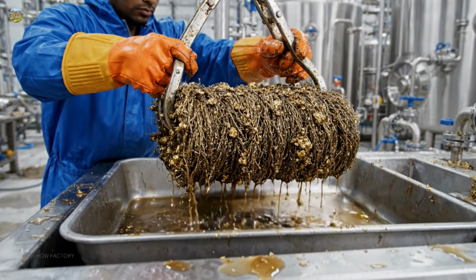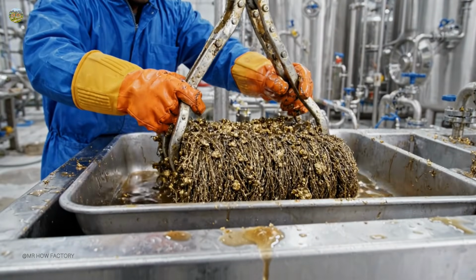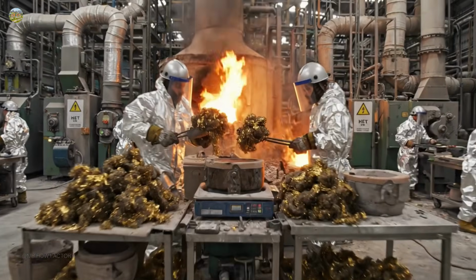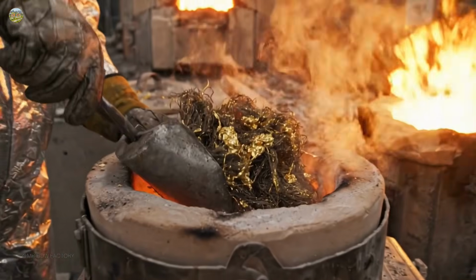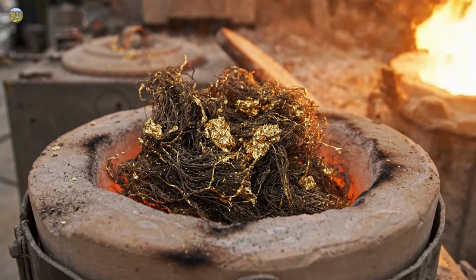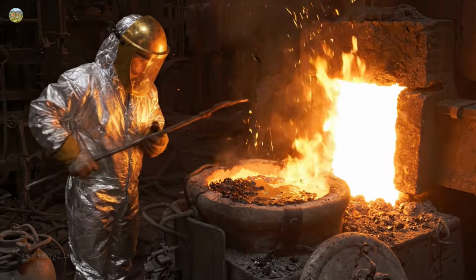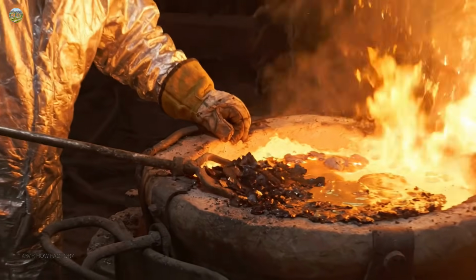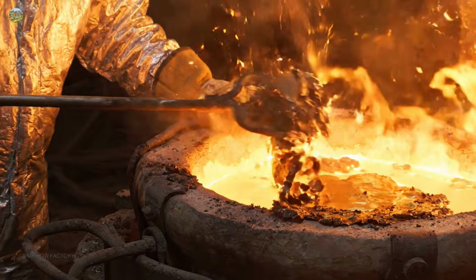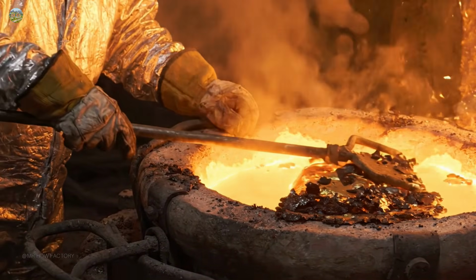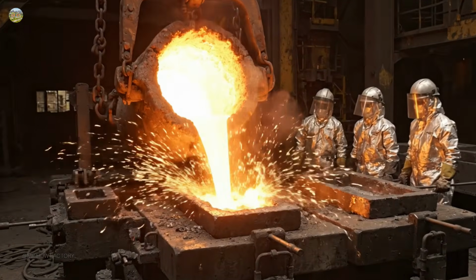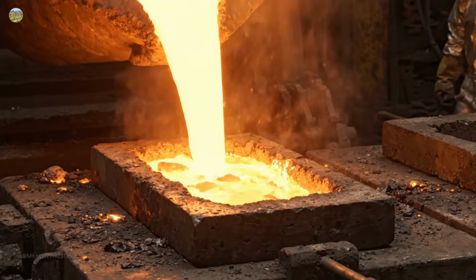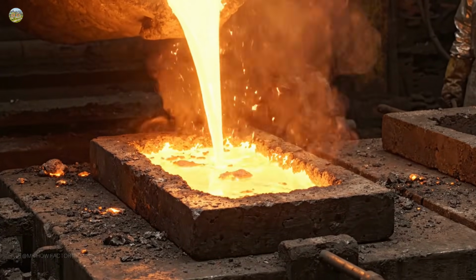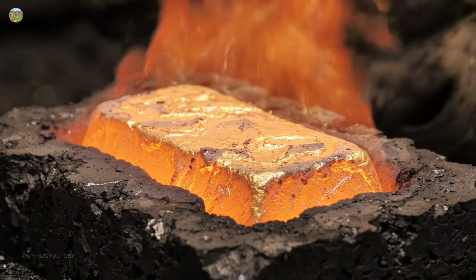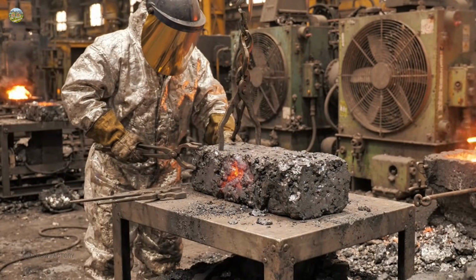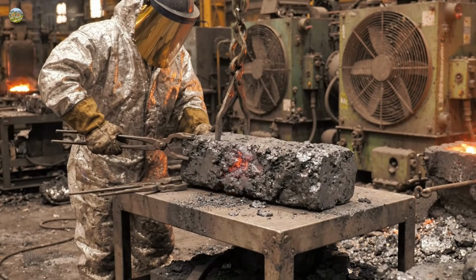The gold-coated steel wool is mixed with chemical powders and placed into a furnace heated to 1200 degrees Celsius. Impurities float to the top as slag and are removed. The molten metal is poured into molds to make a doré bar. This first bar is roughly 60 to 90% gold, mixed with silver and copper. It is not pure gold yet.